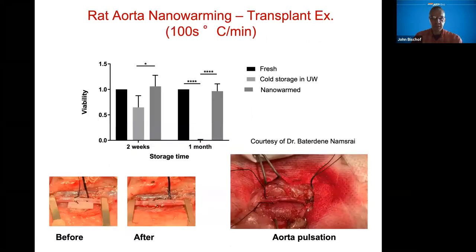So now we've been using that. We've gone past where we were with the original work there in 2017, and we've demonstrated against cold storage. This video unfortunately isn't working, but we've been able to do multiple nano-warmed artery transplantations, and they're good for many months. You can see here for cold storage that after a month you're losing the viability in the cold stored arteries, whereas ours are remaining high in nano-warmed and right up there with fresh. We haven't published this yet, but this is what's coming.